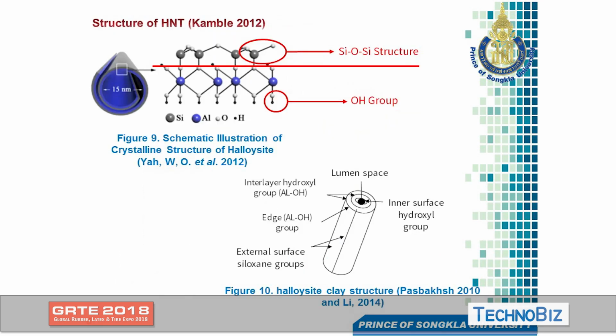They fold together into tubes. The inner surface consists of hydroxyl groups, and the edge also has hydroxyl groups, but the outer surface consists of siloxane groups, just like normal mineral fillers such as clay or silica. In this study, I'm focusing on the use of halloysite nanotubes in natural rubber and seeing what happens to the strain-induced crystallization afterwards. We have observed that halloysite nanotubes can enhance the strain-induced crystallization of natural rubber.